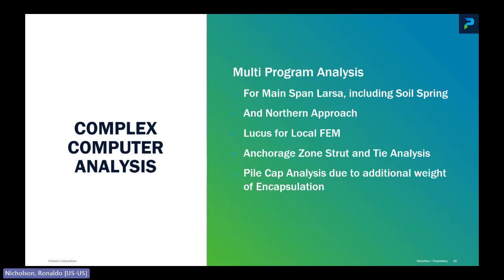Because of the additional loading of the encapsulation, we also redid our pile cap analysis to make sure that we didn't overstress the piles. And of course, we had to make it exciting because that additional load did take the piles to their limits. So we went back, looked at the actual construction piles, loadings, to make sure that we did have the capacity once we did put on this additional weight of the encapsulation.